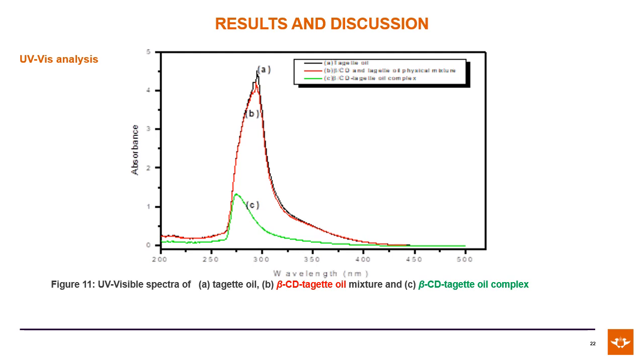UV-Vis analysis was performed on the inclusion complex. The maximum absorbance wavelength of tagette oil was 294 nanometers in the black curve, representing the UV absorption band for a conjugated diene system. The spectrum of tagette oil and beta-cyclodextrin physical mixture showed a peak at 293, which was almost identical to that of tagette oil. However, the absorption maxima of beta-cyclodextrin oil inclusion complex was significantly hypsochromically shifted to 274 nanometers. The shift confirms an interaction between tagette oil and beta-cyclodextrin.